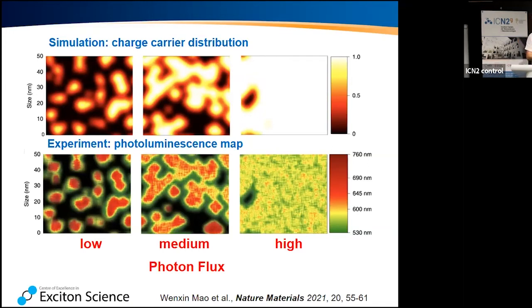Now it turns out that those charge carriers also come with a lattice distortion. In an area where there's lots and lots of charge carriers, if you're an iodide in this mixed halide perovskite, you're slightly bigger than everyone else and you feel somewhat uncomfortable. You're causing lattice strain, and the iodide ions can minimize their lattice strain by moving into one where you have these iodide-rich phases, because that's where the strain is less. So you reduce the strain of the carrier for the iodide. So you have a driving force for the iodide ions to move into areas where there's lots of carriers. And you also have a driving force for carriers to move into that area where you have lots of iodide.